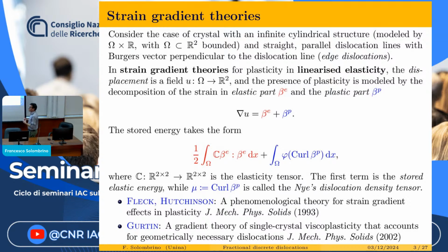So if possible, it prefers to be elastic, but if the elastic energy has become too big, then an elastic collapse appears and the plastic deformation is created. And one is not to be surprised that indeed it is postulated that the plastic deformation is depending on the curl of the strain tensor, if one thinks of our microscopic interpretation. So in some sense, the formation of a defect was related to a circulation condition. Some loop did not close. Some line integral was not anymore zero, but instead was producing a positive result. And this is an integral condition that in differential calculus may be reformulated as a curl condition.